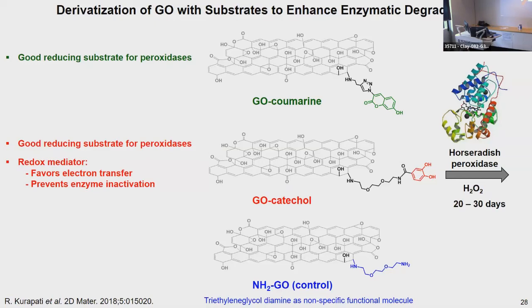Here, our objective was to see if we could accelerate the degradation of graphene oxide by conjugating substrates of the enzymes on graphene oxide. So, for instance, coumarin here and catechol. Both are very good reducing substrates of peroxidases. So, the objective is to attract somehow the enzyme in close proximity to the material and thus facilitate, accelerate the degradation of graphene oxide. In addition, catechol is known to be a good redox mediator in the sense that it can favor electron transfer and prevent enzyme inactivation.